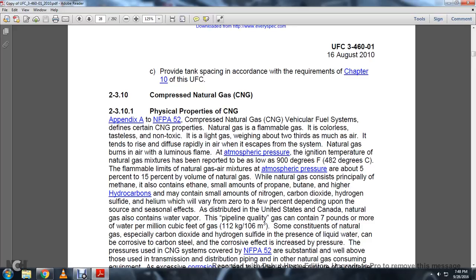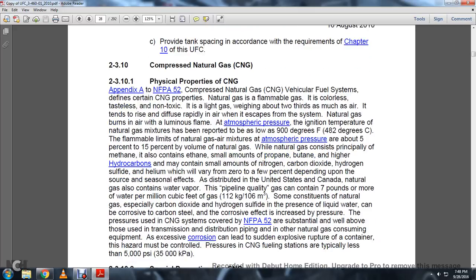Flammable limits of the natural gas mixture at atmospheric pressure are about 5% to 15% of the volume of natural gas. When the natural gas consists principally of methane, it also contains ethane and small amounts of propane, butane, and other hydrocarbons. It may contain small amounts of nitrogen, carbon dioxide, hydrogen sulfide, and helium, which vary from 0 to a few percent depending on the source and seasonal effects. As distributed in the United States and Canada, the natural gas also contains water vapor. Pipeline quality gas contains 7 pounds or more of water per million cubic feet of the gas, and constituents of the natural gas, especially carbon dioxide and hydrogen sulfide.